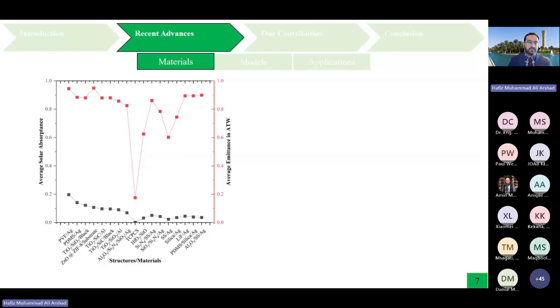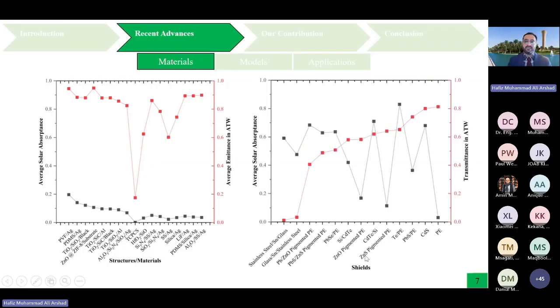So here you see some different structures with different materials. We can see the average emittance in the atmospheric transparency window. You see that PDMS is going to have very high emittance within the atmospheric transparency window. And here you see that the solar absorptance of these materials is extremely low. So they are good materials that can be used for radiative cooling. And some of the shielding materials, as we already talked about, the polyethylene. Here you see that the solar absorptance is really low, but the transmittance in the atmospheric transparency window is really high.